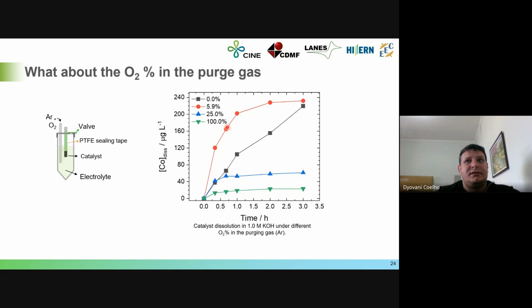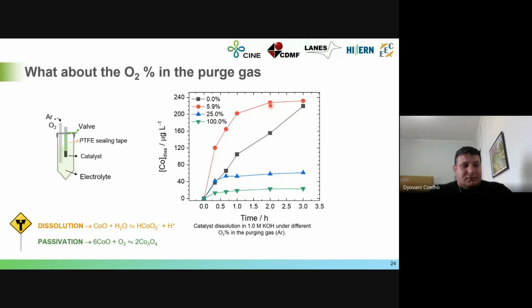We have a huge dissolution starting, but after 1 hour, more or less, the catalyst dissolution tends to stop, which means that with time, the catalyst produces the passive layer and protects against cobalt dissolution. So we actually have a competition between the dissolution of cobalt, because the cobalt oxide is not stable in alkaline medium due to this reaction, and the passivation of the cobalt oxide, producing the high valence cobalt oxide. And this competition means that if we have a lot of oxygen in the purging gas, we can protect the catalyst from dissolution.